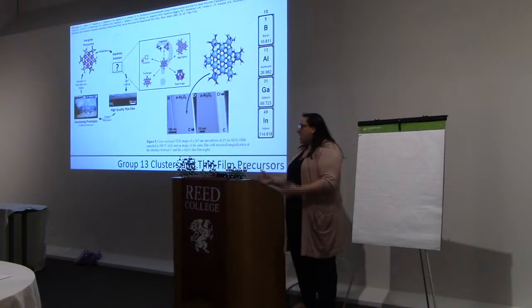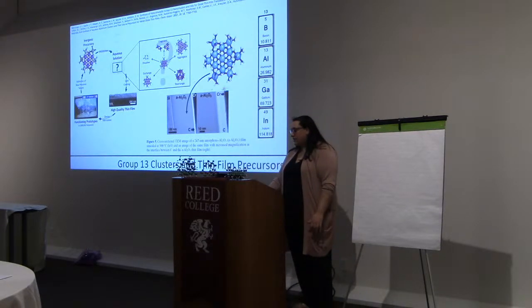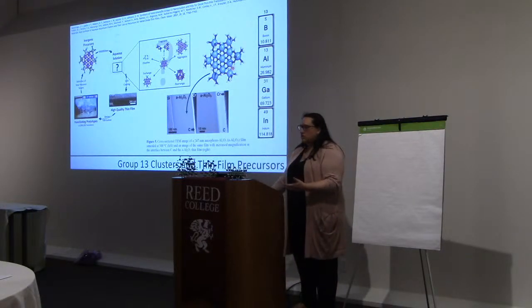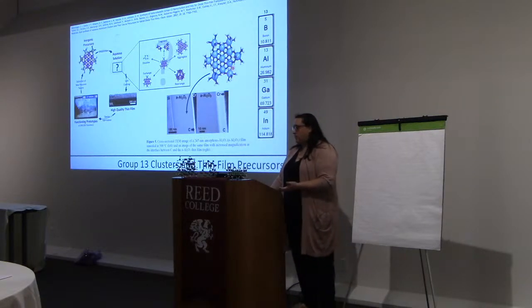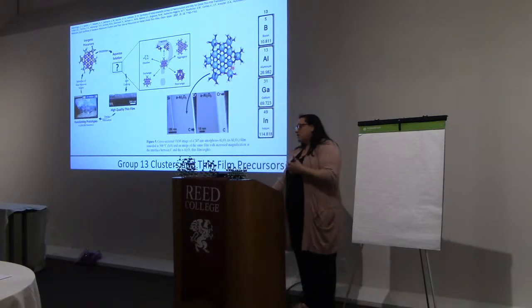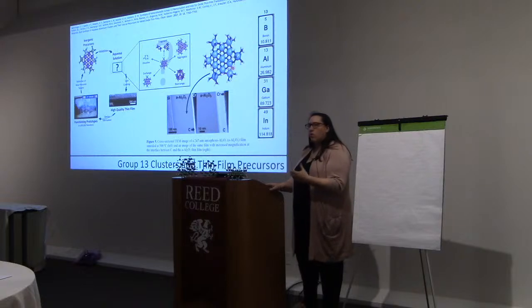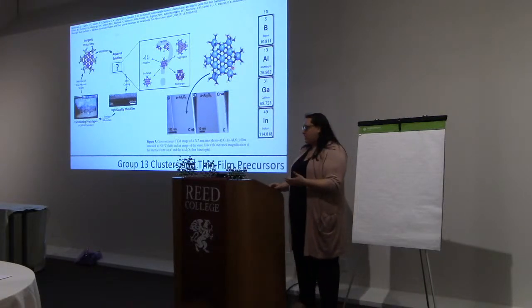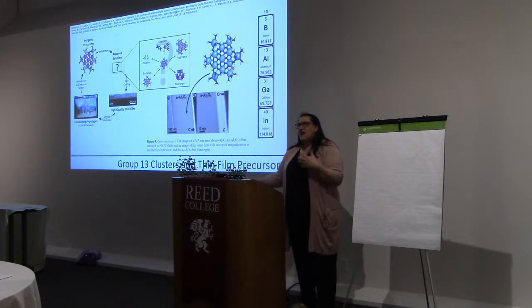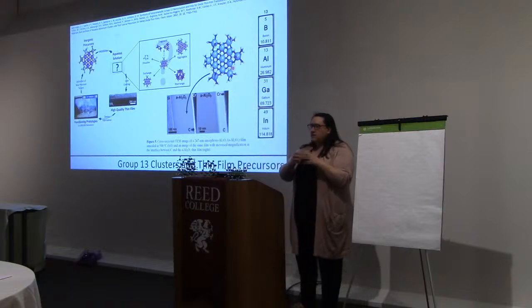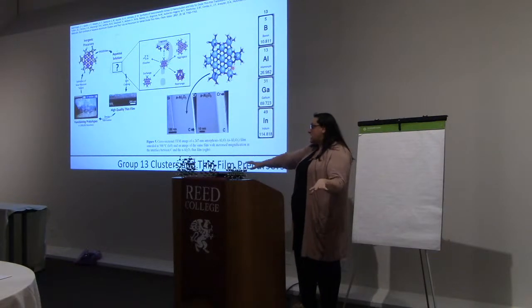The aluminum, there's a similar cluster here, our aluminum, that's a flat, same kind of form. It can also be dissolved into water and spun into a very dense, defect-free aluminum oxide thin film. So that's why in graduate school we were looking at these, and the projects were based around that process of taking small pieces and making an extended network.